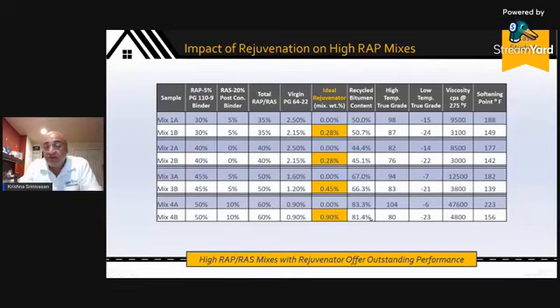So let's just look very briefly at mix 4A and 4B. It has about 85% of your total liquids. In other words, if you're going to add 100 grams of virgin bitumen to a no-RAP mix and you make a mix of this type, you are now only adding 15% of that. The rest of it, you're expecting to come from the RAP.